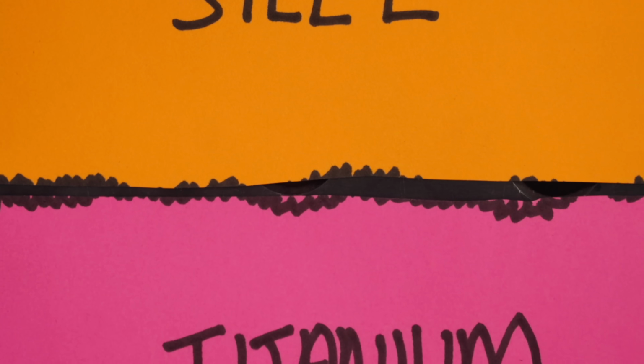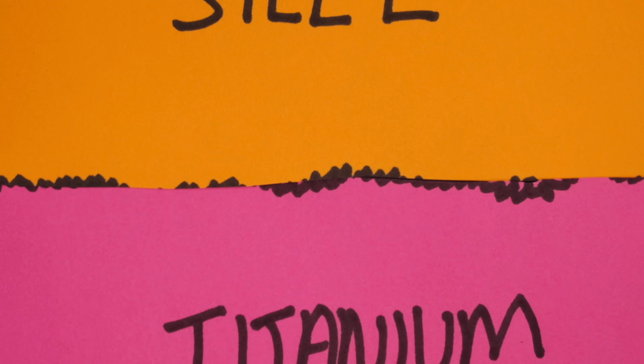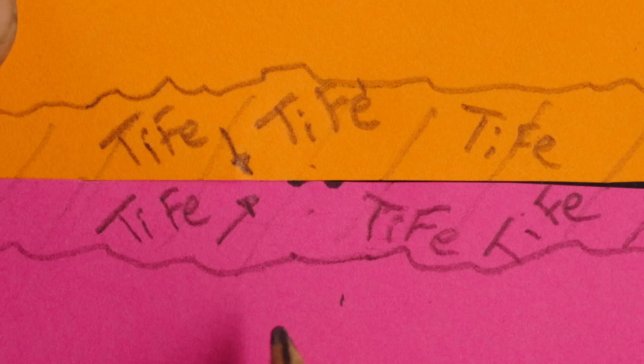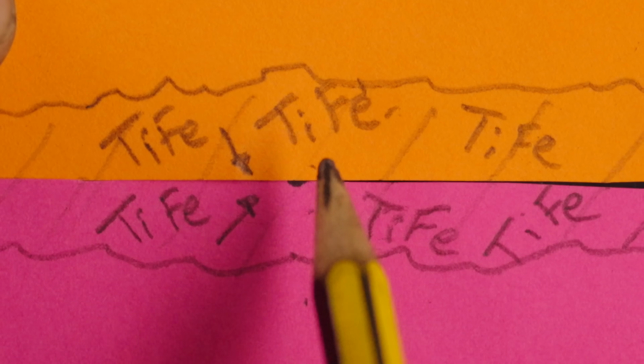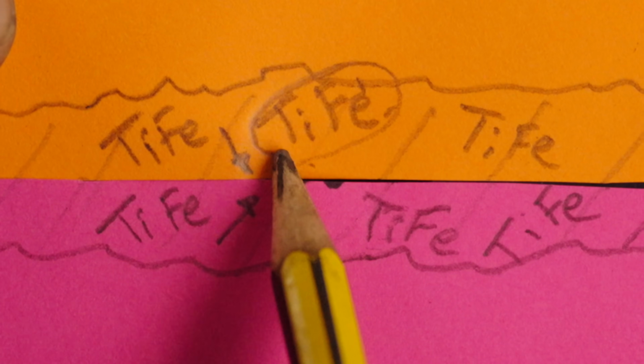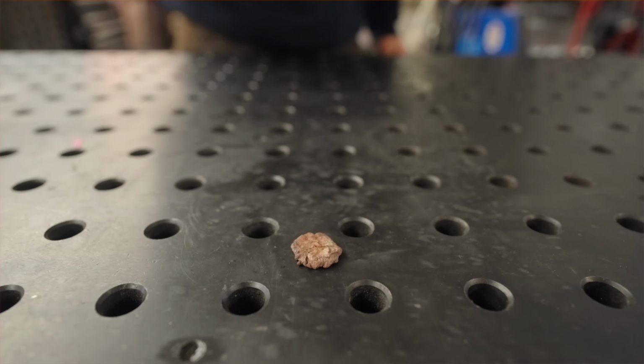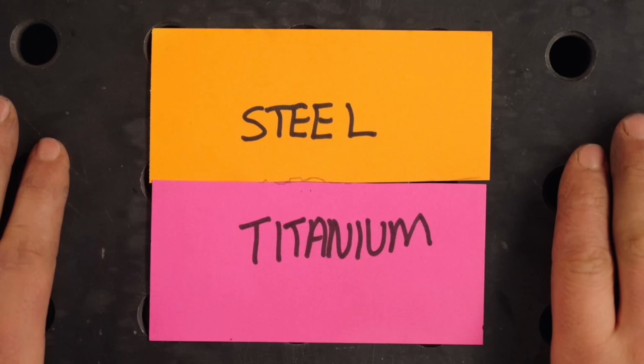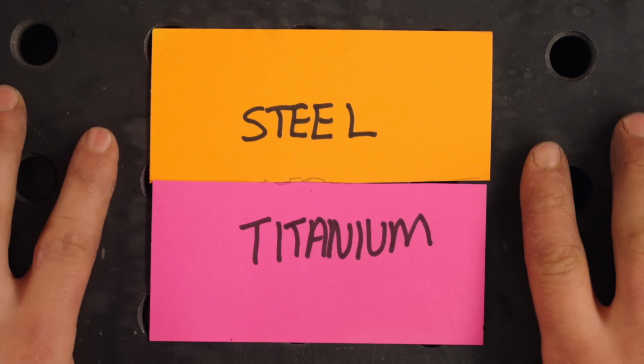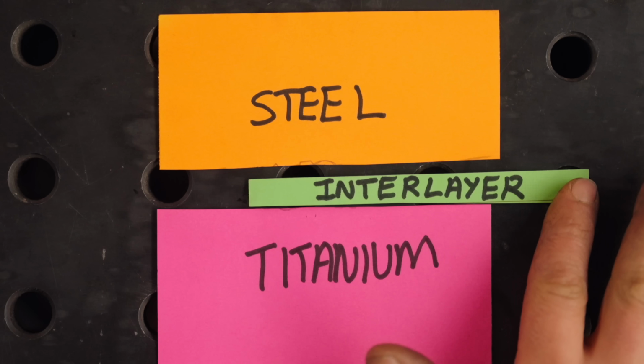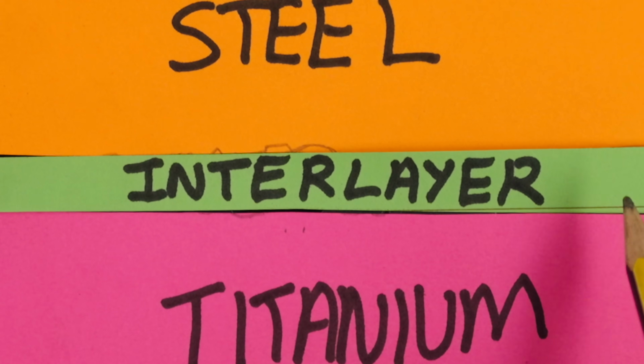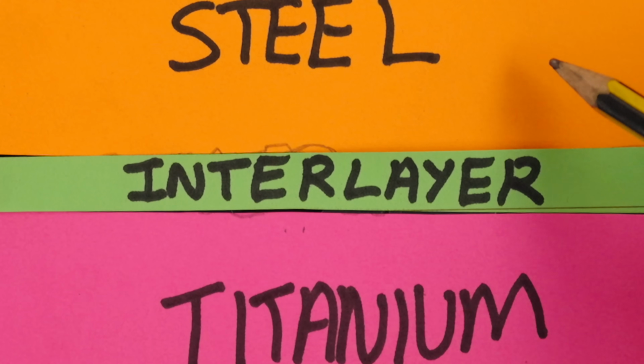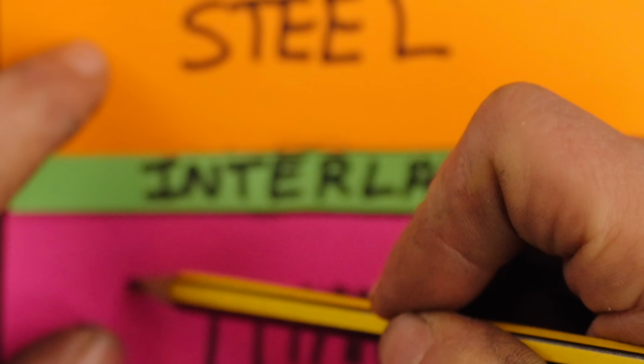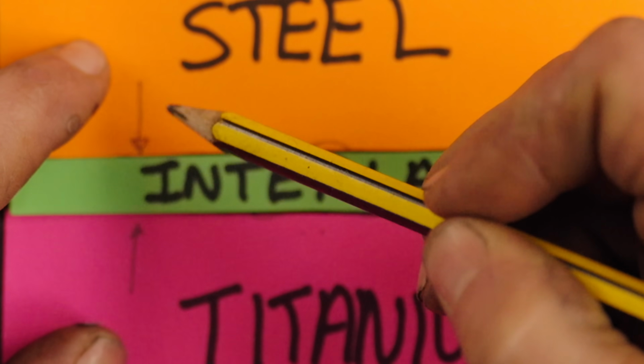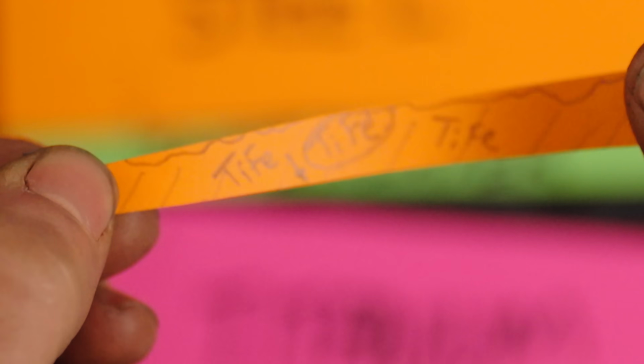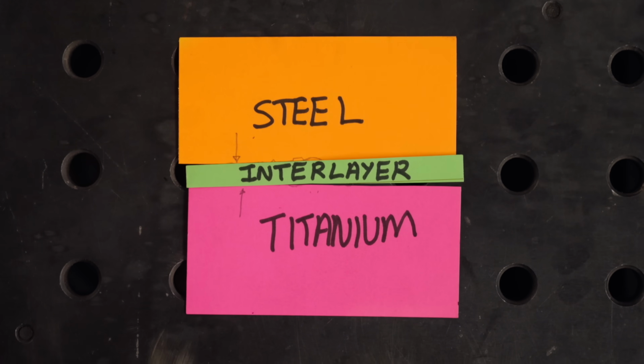When pressure's applied, the asperities deform and the oxides still shatter. The metals do come into atomic contact, but the titanium and the iron react together to make an intermetallic compound, TiFe, at the joint interface, and it is weak and brittle. And that's no good because we want strong joints. So how might we solve this problem? Hopefully with the use of an interlayer. If the interlayer has good bonding characteristics with steel and good bonding characteristics with titanium and stops any interdiffusion between steel and titanium, making that nasty intermetallic compound, we should be able to get them to bond together.